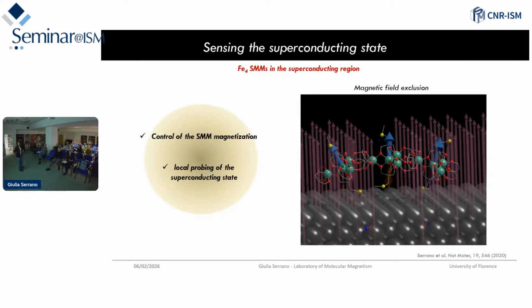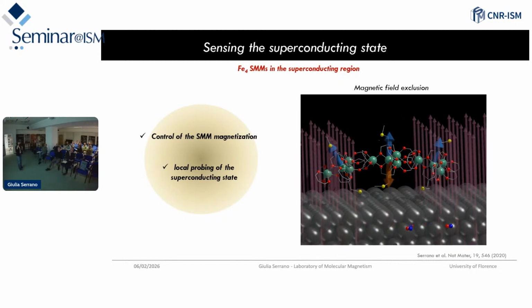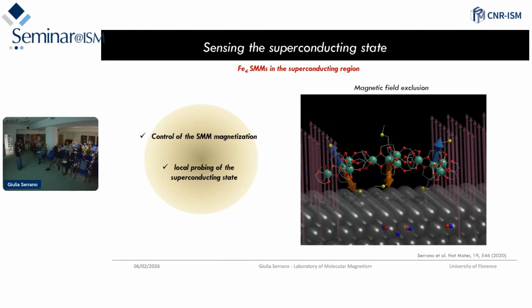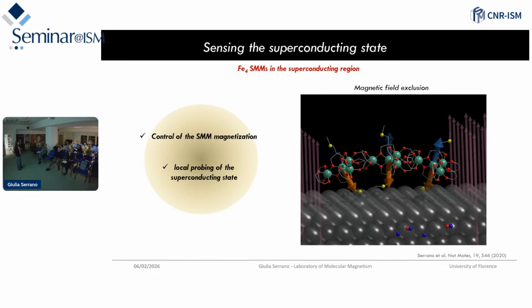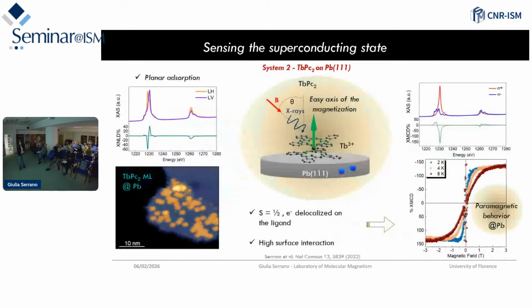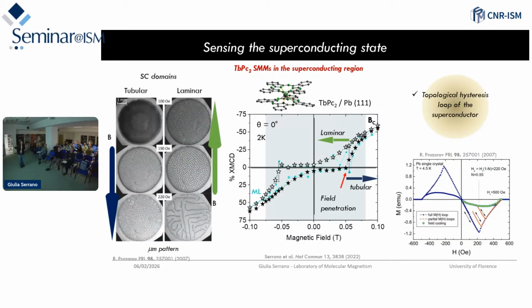So from one side, we had a way to control the magnetization of the single molecule magnet, but we also had a local probe for the superconducting field and for the transition. And we demonstrated this also on another single molecule magnet, the terbium PC2 molecule, in which a terbium ion is embedded between these two phthalocyanine ligands. And here also the hysteresis loop of the molecule is compatible with what we expected from the superconducting side,